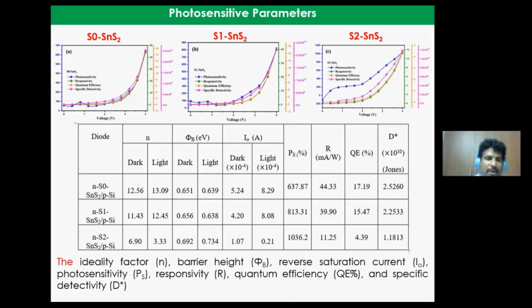Photosensitivity is very high for the flat layered tin disulfide, that is the S2, SnS2-based diode. This is also because in the first sample we have mixing, so photosensitivity is obviously less. For the different structures, the photosensitivity of both S1, SnS2 and S2, SnS2 is somewhat the same, but the difference created with the flat layer is high. So the photosensitivity parameter calculated using IV characteristics confirmed that the flat layers may easily transport electrons from one layer to another layer.